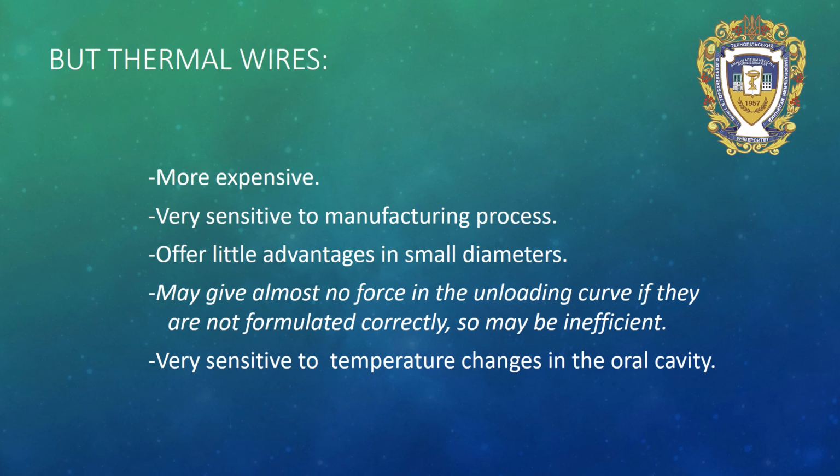But the disadvantages of thermal wires: they are more expensive, very sensitive to the manufacturing process, offer little advantage in a small diameter, may give almost no force in the unloading curve if they are not formulated correctly, so may be inefficient, and are very sensitive to temperature changes in the oral cavity.